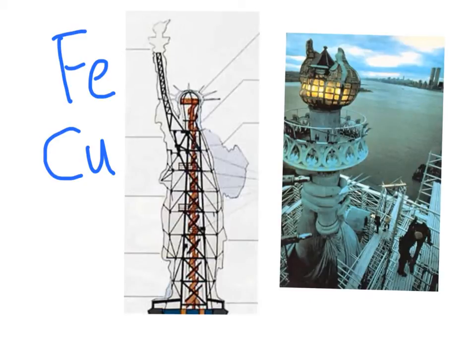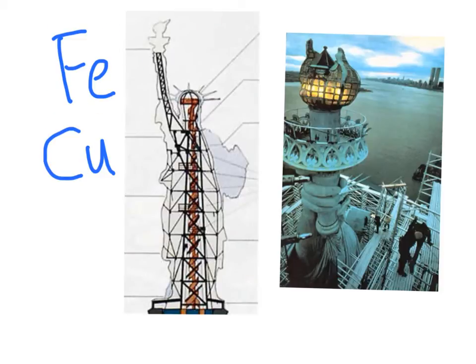The old torch had glass all around and was powered from within. Moisture seeped through the torch, which acted as an electrolyte between the iron armature and the copper skin, enabling the gradual corrosion of the more active iron.